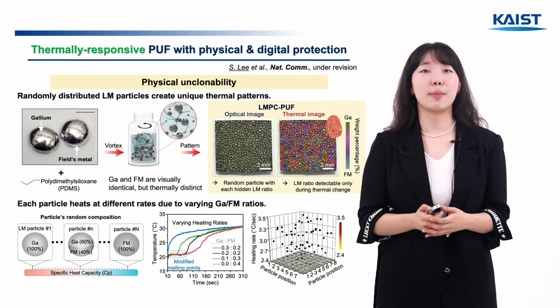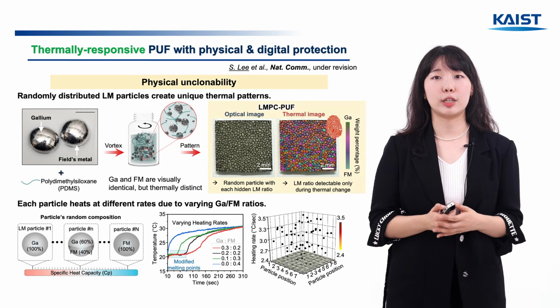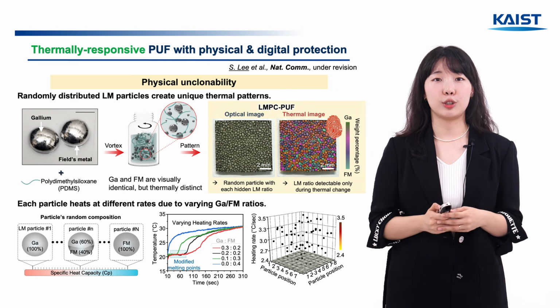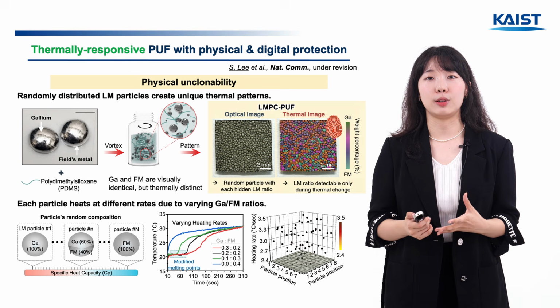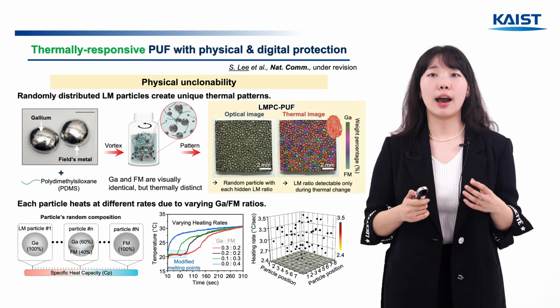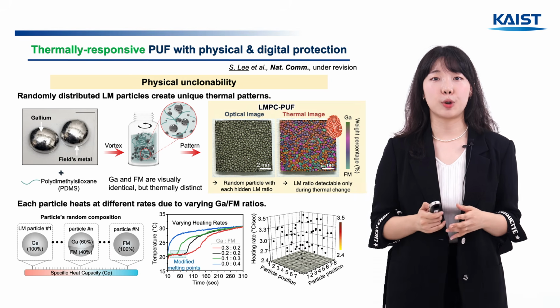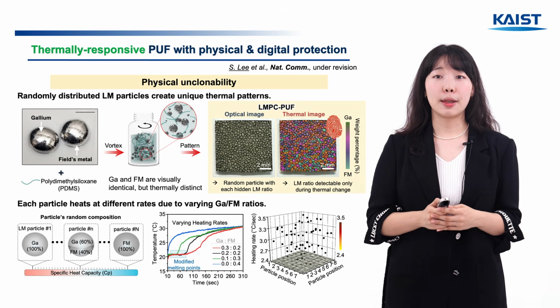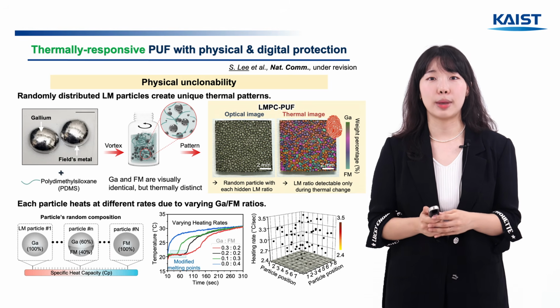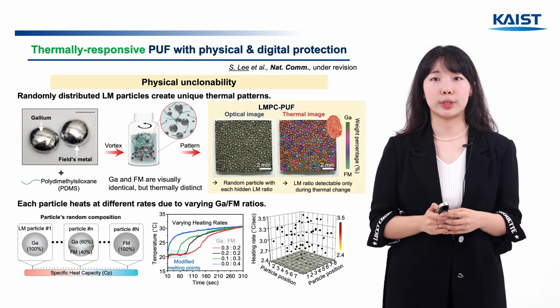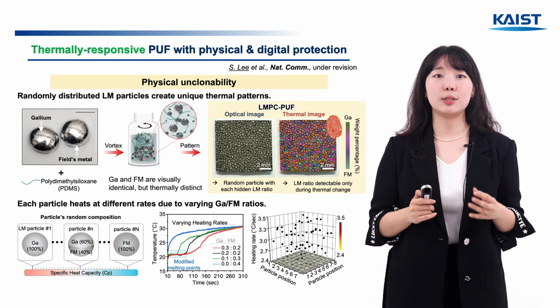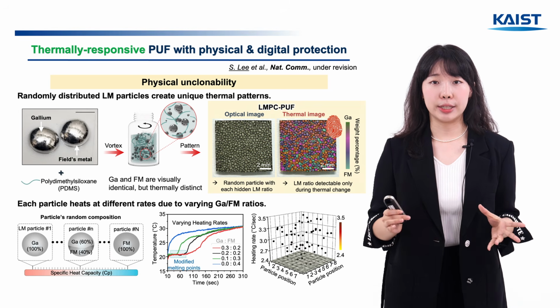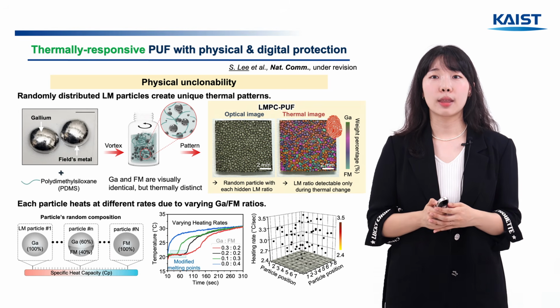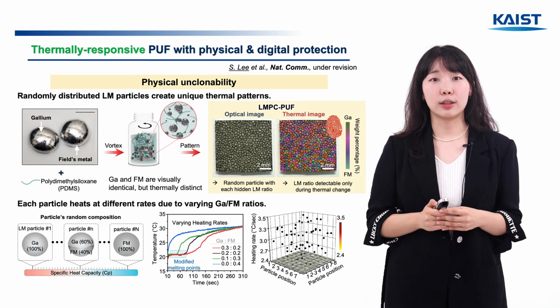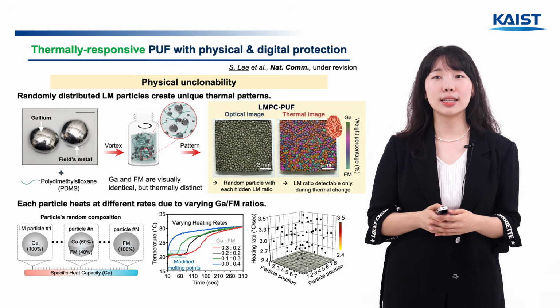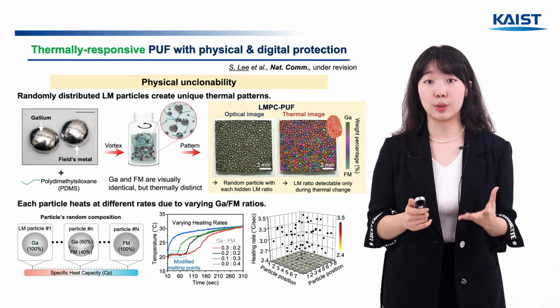To solve this, I made a PUF whose CRPs change in response to temperature, and this PUF is hard to clone both physically and digitally. Let's start with how physical cloning is prevented, which comes from the fabrication process. My PUF is made by dispersing gallium and Field's metal into a PDMS polymer through vortexing. The particles formed this way all vary in size and composition, which makes them hard to copy. And in their liquid state, the two metals look identical to the eye, so you cannot tell the composition of each particle by just looking.